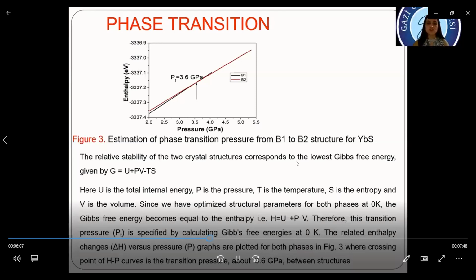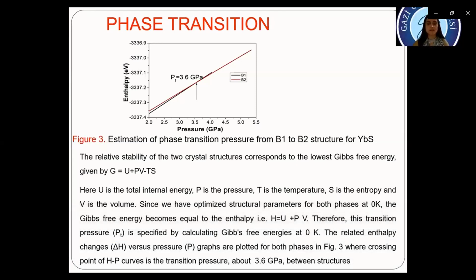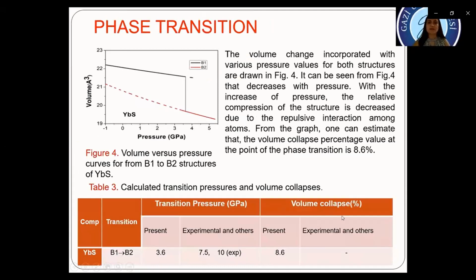The related enthalpy change versus pressure graphs are plotted for both phases in figure 3, where the crossing point of the enthalpy curves is the transition pressure, about 3.6 gigapascal between the structures. The phase transition pressure is 3.6 gigapascal. The volume changes with various pressure values for both structures are drawn in figure 4.